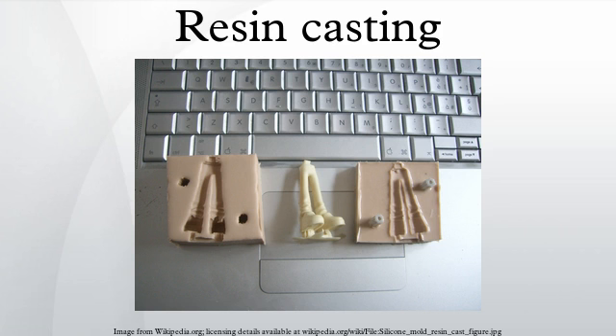Typically, a flexible mold will yield between 25 and 100 castings depending upon the size of the part and the intensity of the heat generated. Depending on the type of product, it may then be cut or sanded to remove any casting artifacts like sprues and seams.